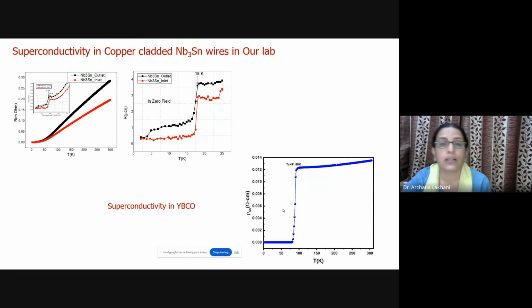These are some graphs of resistance versus temperature for some samples which we have measured in our laboratory. This is an Nb3Sn superconductor which superconducts at around 18 Kelvin, and these are copper cladded. From the application point of view, some copper cladding was done on this. We got these samples from IPR, Gandhinagar, Gujarat. A group there is actively working on these copper cladded Nb3Sn and NbTi wires, and we measured the resistance for them.